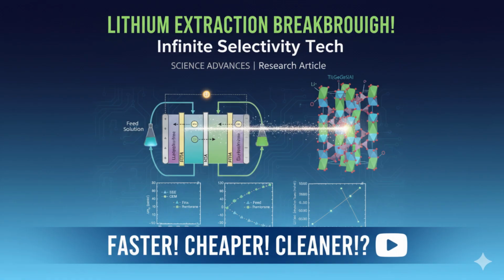Okay, that explains the lithium versus sodium selectivity. What about other common ions like magnesium, Mg2+? Sometimes divalent ions can be smaller than monovalent ones, right? They can be in terms of their bare ionic radius. Yeah. But magnesium runs into other problems. It's about charge exclusion and energetics. How so? Firstly, getting a doubly charged ion like Mg2+ into the lattice site designed for a singly charged Li+ creates charge imbalances. There's an energetic penalty associated with creating the necessary defects in the crystal structure to accommodate that higher charge. Secondly, magnesium ions have a much higher hydration energy than lithium. Meaning it takes more energy to strip off their water shell. Exactly. They hold on to their water molecules much more tightly. So the initial step of getting dehydrated at the membrane surface is much harder for magnesium. Combine the difficulty of dehydration with the energetic cost of entering the lattice, and divalent ions like magnesium are effectively barred from entry too, even if their bare size might seem okay.